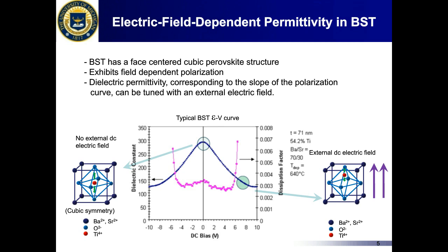The Curie temperature for the material can be adjusted by changing the stoichiometry of barium-strontium within BST. Typically, we use a 50-50 material with a Curie temperature of about minus 50 degrees C. The permittivity in the material is a function of applied bias or electric field. The dielectric constant versus DC bias is symmetric — whether we apply negative or positive bias to one electrode, tunability varies symmetrically. The loss tangent for the material is also shown; the Q of materials, which is one over loss tangent, is several hundred. One can fabricate materials with high Q and electric tunabilities typically greater than 3-to-1.